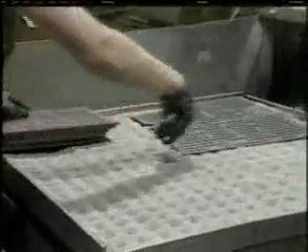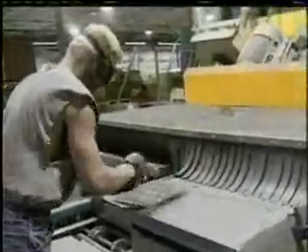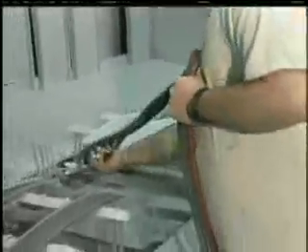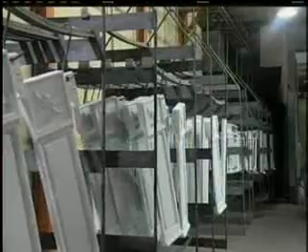In the preparation process, the castings are blasted with chilled iron grit to remove any residue. This ensures a very clean casting and gives the surface a rougher finish that adds to the adhesion of the enamel. The castings are then sprayed with an enamel base coat that seals the surface. After being fired in an enameling furnace, the castings are put back on the spray line where they receive a final decorative coat. Then they are fired again.